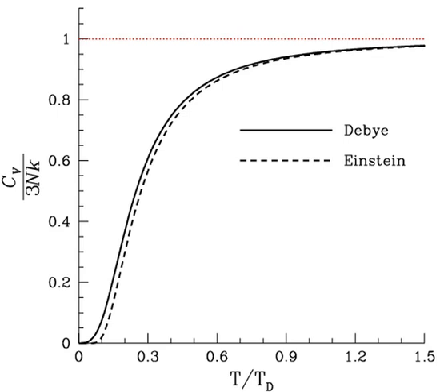As noted, heat capacity values far lower than 3 R per atom, as is the case with diamond and beryllium, result from freezing out of possible vibration modes for light atoms at suitably low temperatures, just as happens in many low-mass atom gases at room temperatures where vibrational modes are all frozen out. Because of high crystal binding energies, the effects of vibrational mode freezing are observed in solids more often than liquids. For example, the heat capacity of liquid water is twice that of ice at near the same temperature, and is again close to the 3 R per mole of atoms of the Dulong-Petit theoretical maximum.